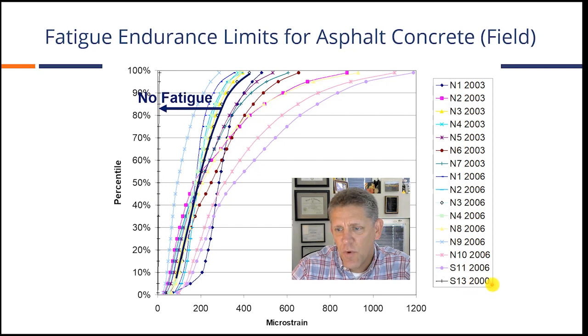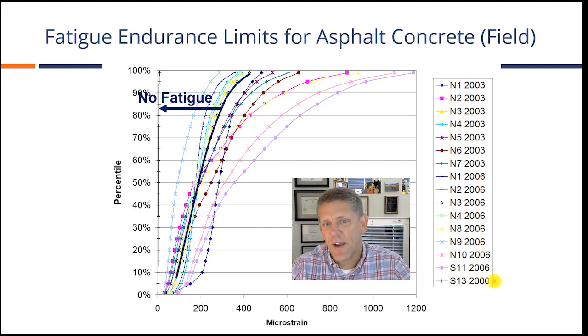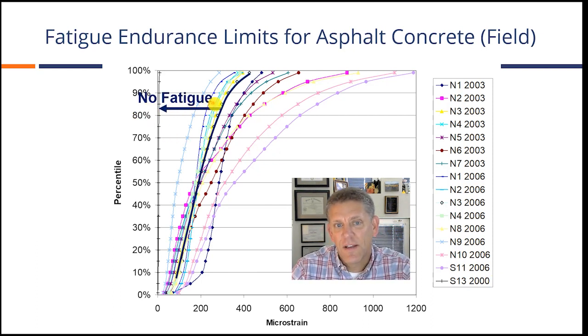This is actually one of the original test sections at the test track that was 2 feet thick of asphalt, had extremely low strain levels, and was designed purposely not to have bottom-up fatigue cracking because of the objectives of that first test track experiment. And it's super conservative. And then you have things that are a lot less conservative, but every one of these sections did not experience bottom-up fatigue cracking.